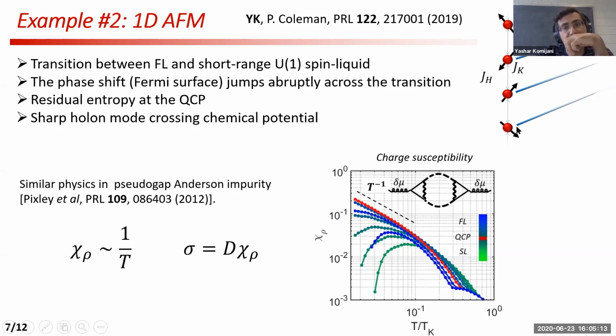Now, in this case, the holons are local. They are located at the positions of the impurities, and they do not move around. But if somehow we could imagine that these holons could diffuse around incoherently, then the conductivity of the system would come from the Einstein formula, a diffusion constant D times the charge susceptibility. And if D is constant, then I would get a Curie conductivity, or a linear T resistivity. This is just pure speculation. Of course, I cannot compute the D in the system, and they are not even moving here. But it just gives some intuition that probably this charge susceptibility is tied to the linear T resistivity.